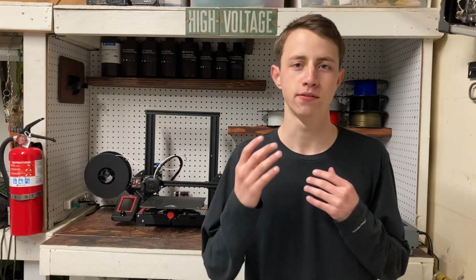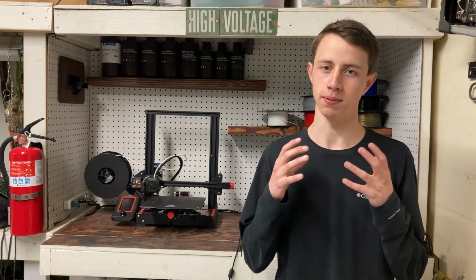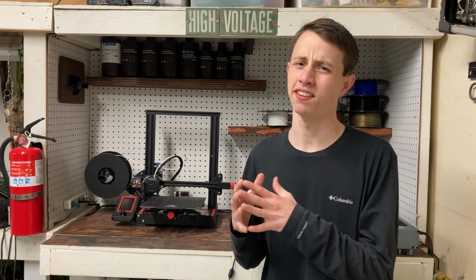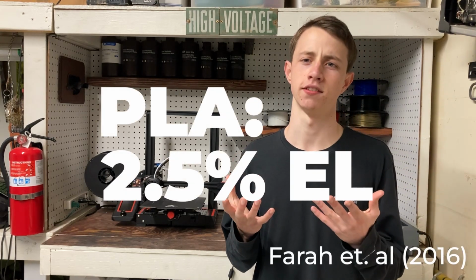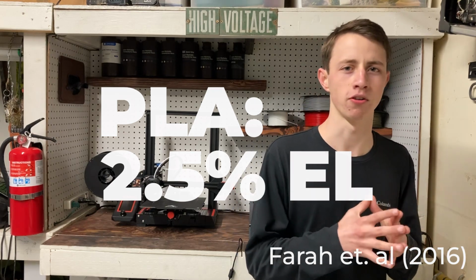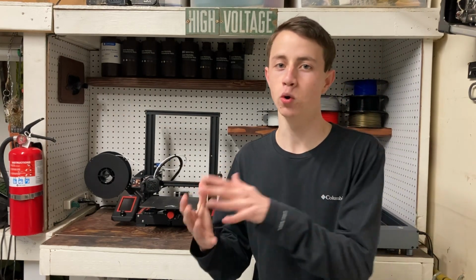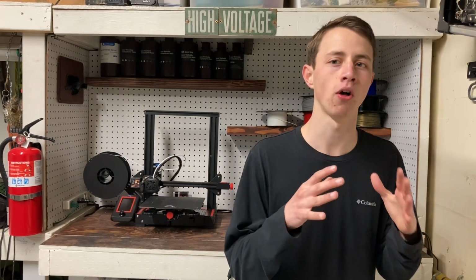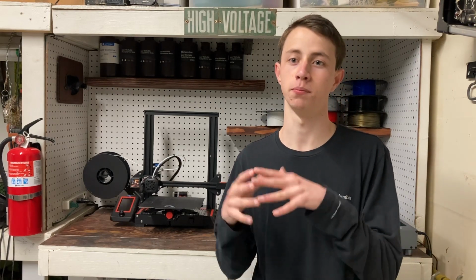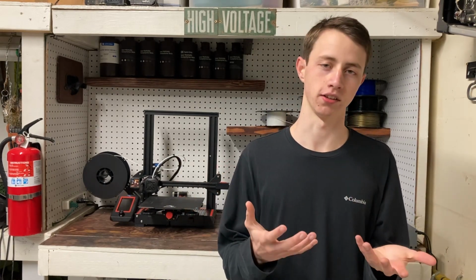Now, one of the key factors that's limited PLA's ability to replace oil-based plastics is its lack of ductility. PLA is more brittle than oil-based competitors like PET, with an elongation at break that hovers around 2.5%. What the study by Farah et al. suggests is that heat treatment post-PLA production is a viable alternative to adding natural fibers before production to increase ductility.